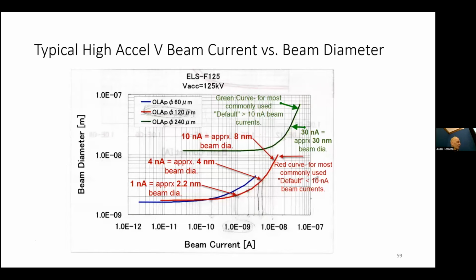So in terms of beam current and beam size, we have this plot here of the Elionix nominal beam current at one of the aperture sizes, which goes from about 10 nanoamps up to about 100 nanoamps. We get this curve. We're looking at beam diameter in a log scale against beam current in a log scale. And if you look at the slope here, the slope of this is very similar to the slope of this.